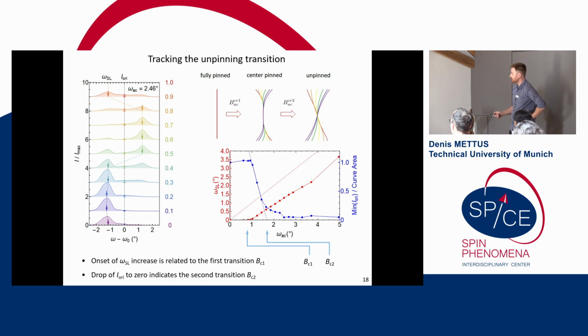You see that at a certain critical threshold you begin seeing the motion, and then it increases linearly. So we are not able to reach any kind of saturation of this curve, compared to the old results. And this is the intensity at the center, which tells you how much of your skyrmion phase is still pinned. It begins dropping down right when you begin seeing any motion.